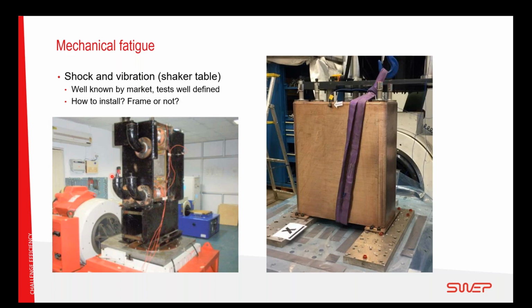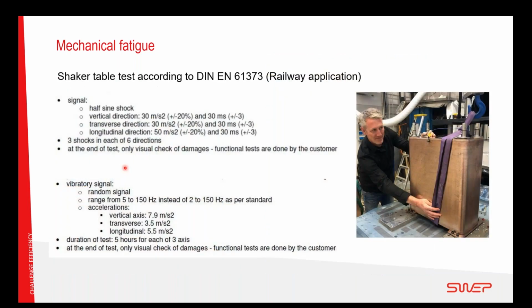To the right is a test we did on our heat exchanger. Some more details about this. It's a test we did. The standard is taken from a railway application, EN 61373. It's shock and vibrations. And here is the test described, the shock loads in each of the 3 directions. You go plus minus in both directions, so that's 6 shocks that are done on the heat exchanger. Since we don't know exactly in what direction the heat exchanger is mounted, it's been tested here for the highest value for all directions on our heat exchanger.